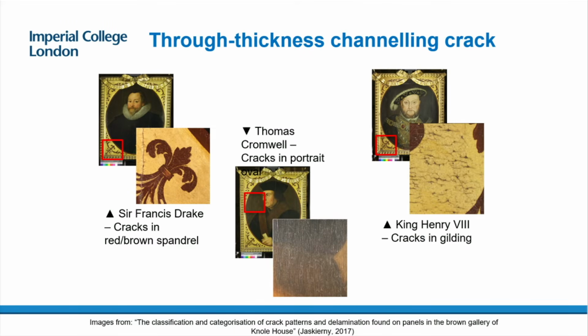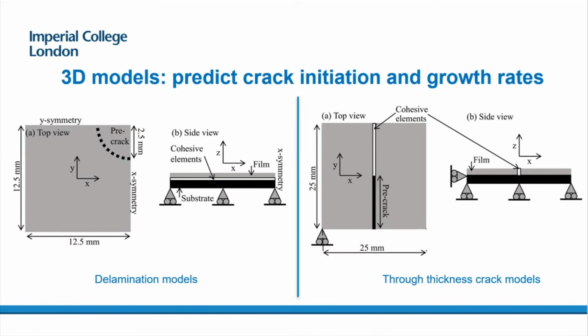The second type of crack is a through thickness crack. So this is a crack that happens normal to the plane here. So you can see it here, King Henry VIII. You can see these cracks are going through the layers, but also propagate along the painting. And you can see it here on the actual portrait, which is more severe, of course. And there's also some here as well. So these are the models that we built to try and predict when cracks will form as a consequence of this fluctuating humidity and temperature.